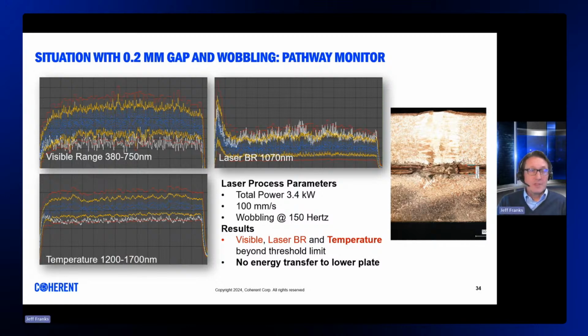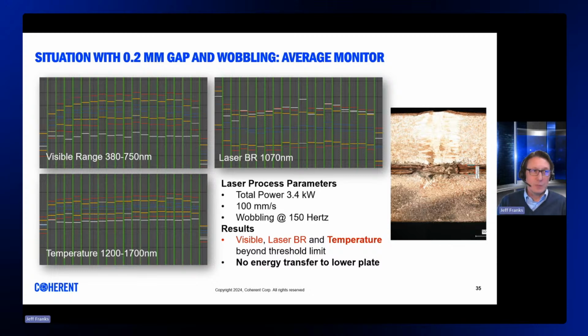Finally, the gap has now been increased to 0.2 millimeters, though other conditions remained unchanged. All signals have passed the error condition, and a weld joint was not created due to no energy transfer into the lower 1 millimeter copper plate. And again, we see the corresponding data when shown through the average monitor.